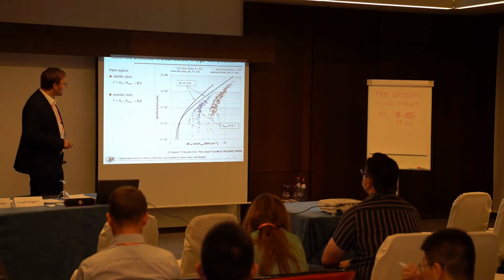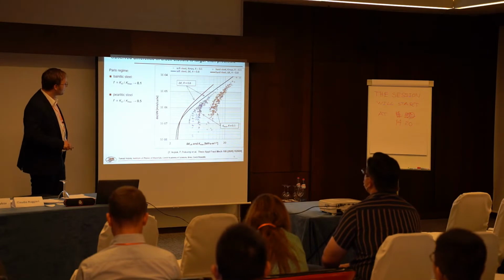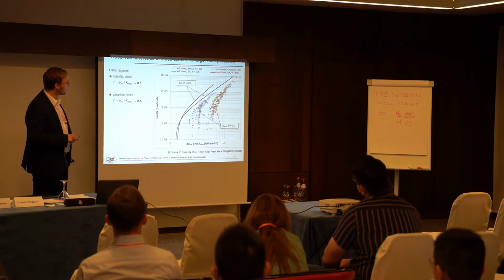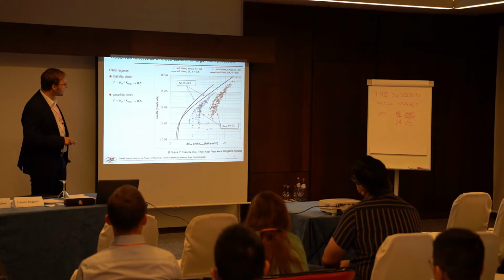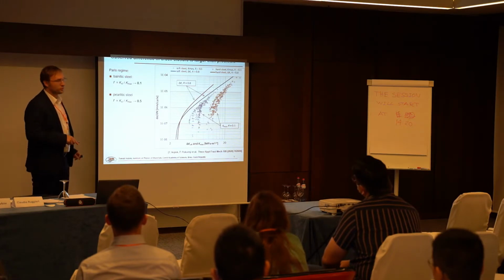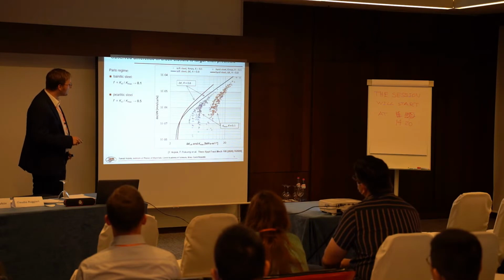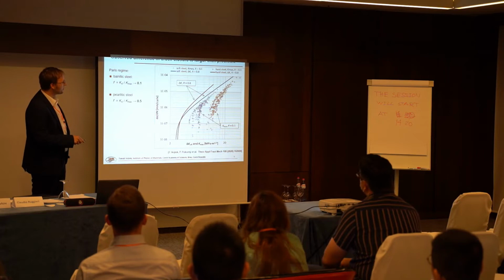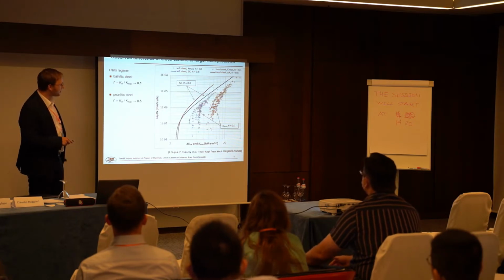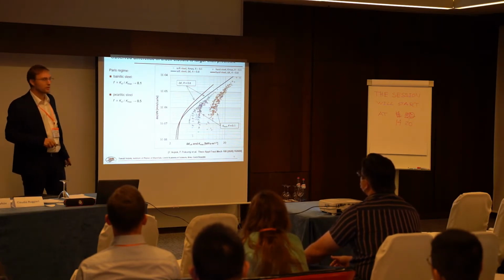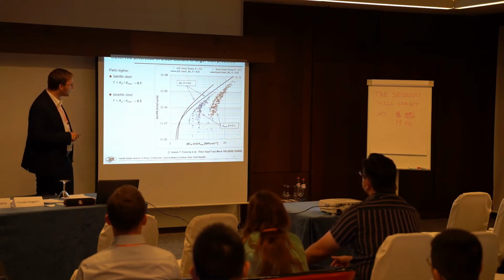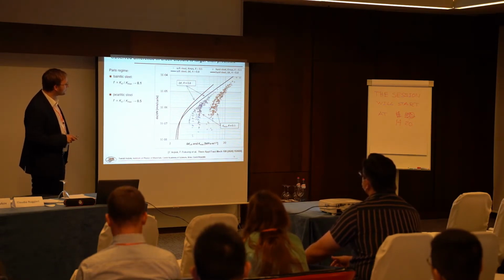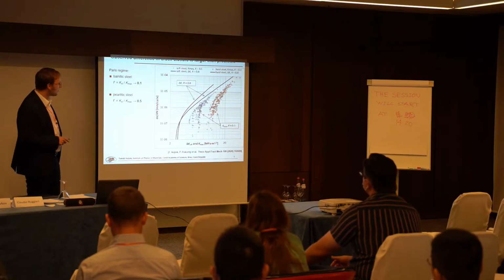Because we have different plasticity induced crack closure effects in various materials, and here we have two steels, and we have the crack growth rates here for load ratio 0.8, which is a non-closure ratio, and then we have data for 0.1, where crack closure was present. And we have delta K effective for the R 0.8, and we have K maximum for R 0.1. So the difference between these curves should be crack closure value. And we can see that for one of the steels marked by dark blue, we have quite small value of closure, and in case of the red steel, we have quite big difference.